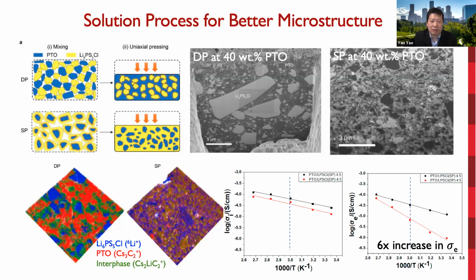We note here that typically reactions between cathode and electrolyte are to be avoided or suppressed. For example, coating on NMC particles, an oxide coating, is used. However, here is an example showing that the reaction between the cathode and electrolyte can be used for the benefit of forming a better microstructure.